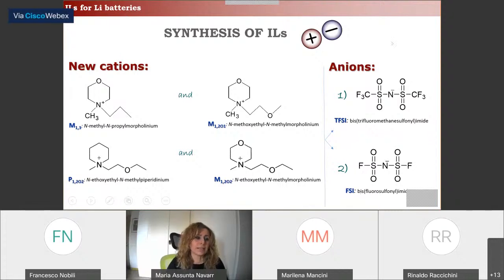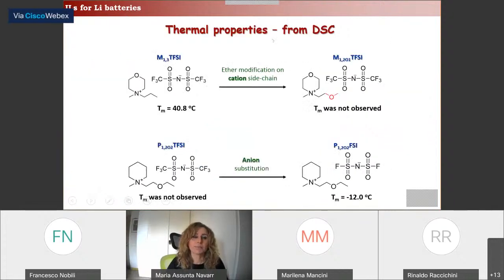Of course, the thermal properties in terms of crystallization of the ionic liquids are strongly affected by both the oxygen modification or the anion structure. For example, an oxygen in the side chain increases the flexibility of the structure, thus suppressing crystallization. On the contrary, a smaller anion structure can enhance the crystallization of the compound.